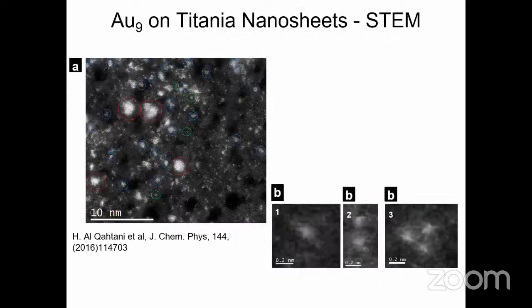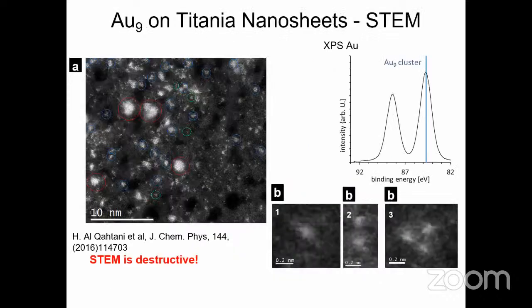We know the world is not perfect, and that's why we get some aggregation already because of the electron beam. But we also get some fragments of this nanocluster, where we have single atoms, dimers, and trimers, which are just three atoms. And we report them also with the XPS finding. This is the gold nine cluster. It's exactly what has been reported in our previous papers using the synchrotron itself.